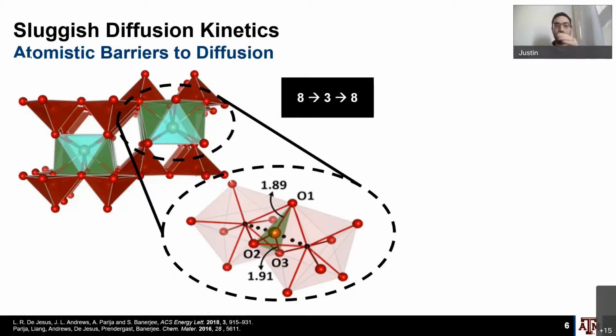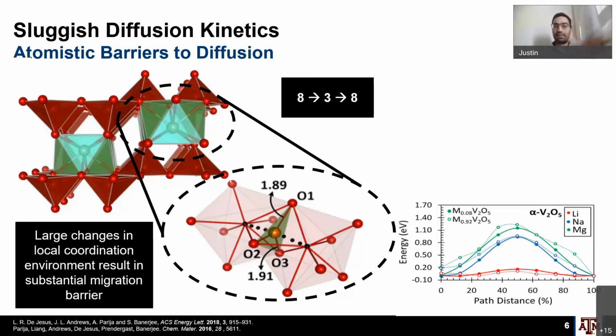And so as lithium diffuses through the lattice, it actually goes through a relatively significant change in coordination environment. So it goes from an 8-coordinate site to a relatively constricted 3-coordinate site, and then back to an 8-coordinate site. So there's a lot of bonds between lithium and the harder oxygen lattice that have to be broken and reformed as it diffuses. So this can be quantified through nudged elastic band calculations and examined as a function of what's diffusing through the lattice.